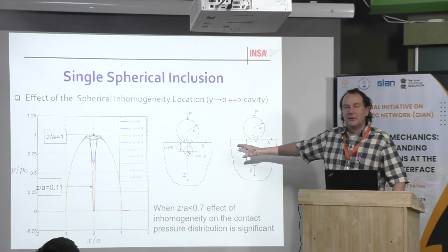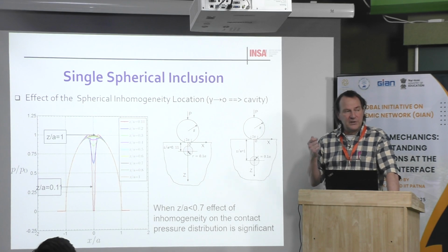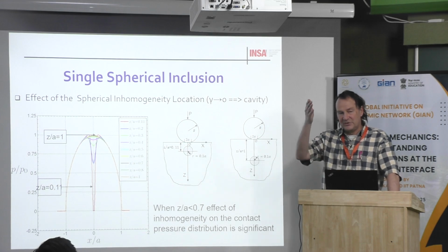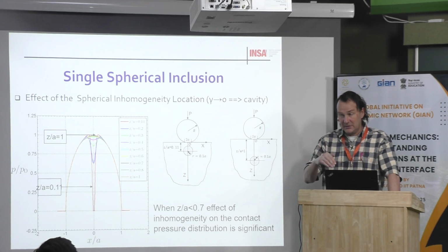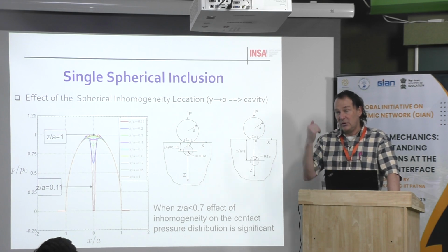Then maybe from that, what I can say is the idea is if you deal with contact between composite materials and homogeneous material, if you do not want to have an effect, for example, I speak about a composite blade on a steel disc, you have to manage to have the fibers far from the surface. And if you know the Hertz contact dimension, you should put the fiber at least at the Hertzian contact half width or contact radius. And if you do that, you will have no effect of the inclusions on the pressure distribution and the risk of failure of the other material.